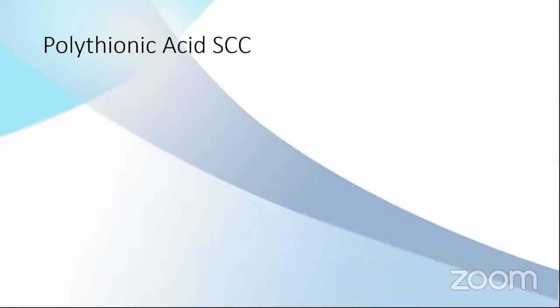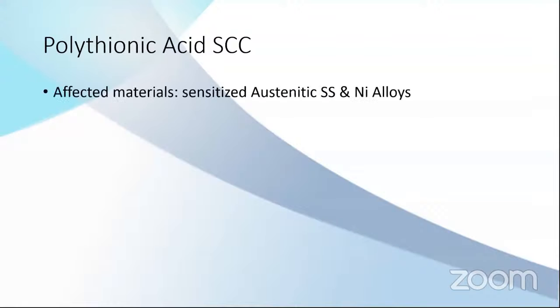Just to remind again, this is very important because it happens rapidly, very often unpredictable, and almost all weldments are probably susceptible because they already have the stress inside the weldment, the residual stress. So most of the mitigation will be related to the reduction of the residual stress or post-weld heat treatment.